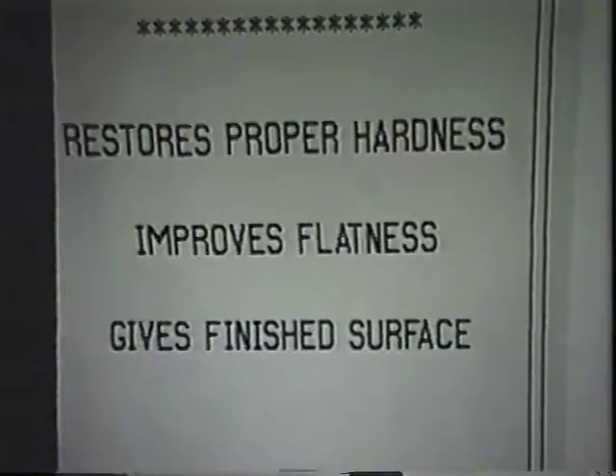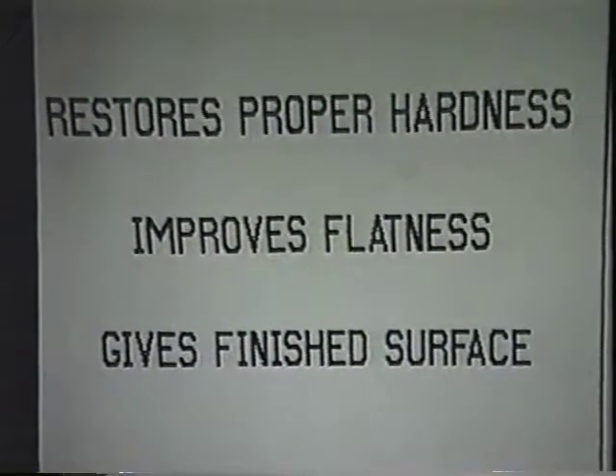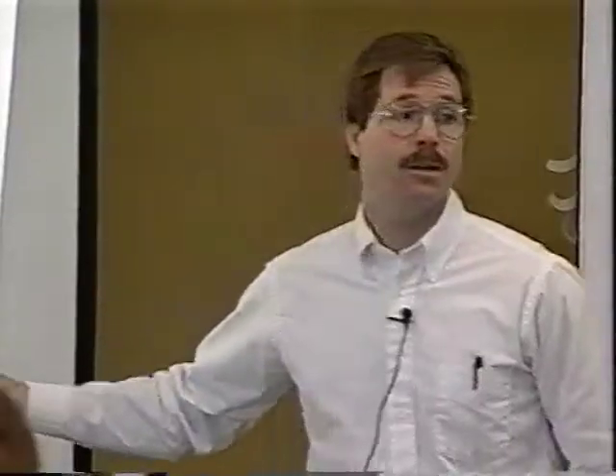But not only do we restore the proper hardness through the tempering process, we also improve the flatness a little bit. Through the anneal, you get some distortions. We don't remove those. And we provide the matte finish that's required, okay, for exposed applications. We do that through texturizing, through blasting or electrical discharge texturing, EDT. We put a surface on the work rolls that's going to be imprinted on the steel itself. Okay.